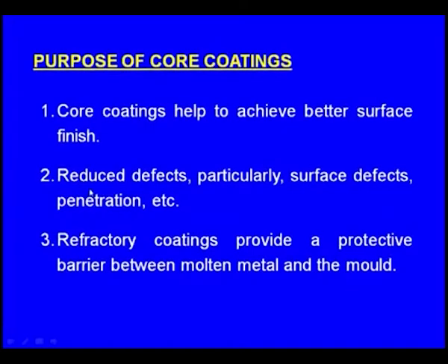Core coatings help to achieve better surface finish, and they also help us to reduce defects, particularly surface defects like penetration. If the sand grains are somewhat larger, there will be some clearance between the neighboring sand grains, and the hot metal can penetrate into the clearance between two neighboring grains, and that results in the penetration defect. So, when we give this core coating, the possibility of the penetration defect comes down.